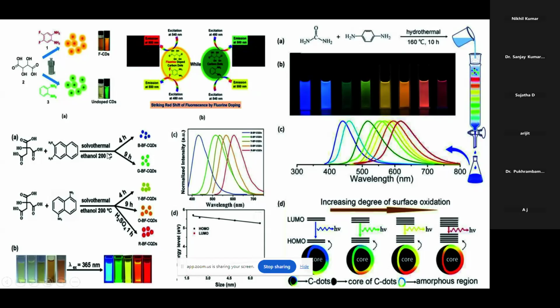Then the solvothermal process is simple, like hydrothermal. Solvothermal uses some solvent other than water. Here we used ethanol at 200 degrees Celsius for 4 hours. We can get blue emission of CQD, and if we keep it for 9 hours, we get the same thing with green emission. According to our desired application, like fingerprint region detection or forensic applications, we go for green or yellow, the desired emission we want. Then another one is solvothermal at 200 degrees Celsius with 4 hours, 9 hours, and with H2SO4 acid as solvent. With that, we can achieve red emission CQD.